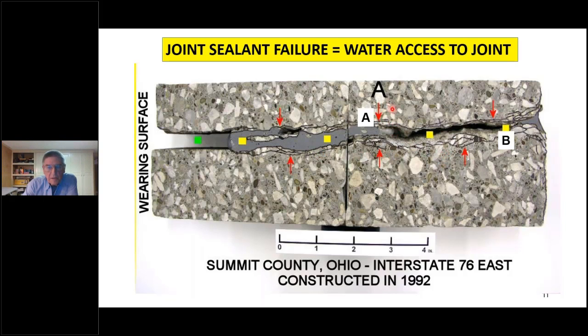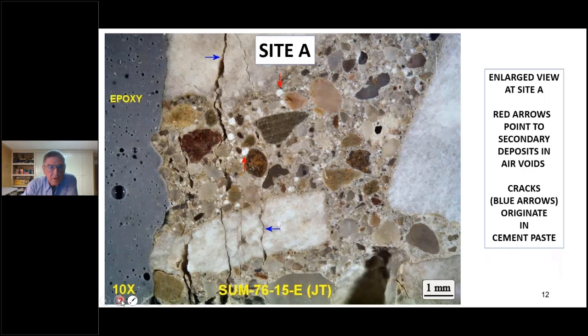So we would expect that the deterioration would continue over cycles of wetting and drying and freezing and thawing. And eventually, with support loss, we would start to lose the section up here. At the bottom of the core there, we're seeing the beginning of that cone-shaped type of failure as well. And what we're going to do in the next two slides is to show even closer, microscopic pictures of this area, which we'll just designate as area A, and then the area at the bottom, which I'll designate as area B. And we'll be looking at this under the microscope to get a clearer picture of what's going on.